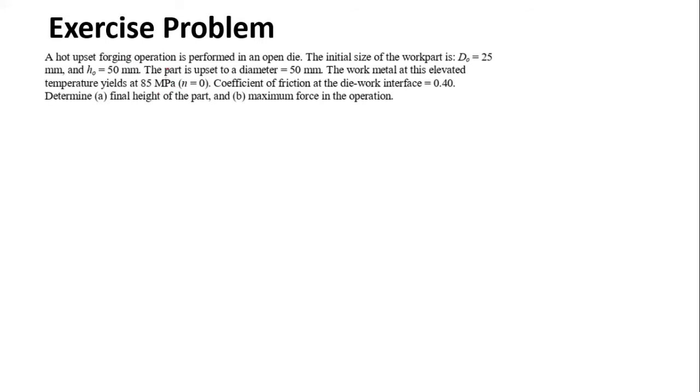So it means, as we know that we are performing hot forging, we have the strain hardening equal to 0. And we have studied while discussing hot working or hot forging that when we are performing hot forging, we take the flow curve equal to the yield strength of the material. So in this case we have 85 megapascals. The coefficient of friction at the die work interface is 0.40. Determine the final height of the part and the maximum force in the operation.